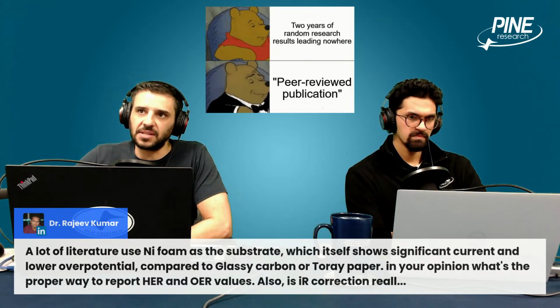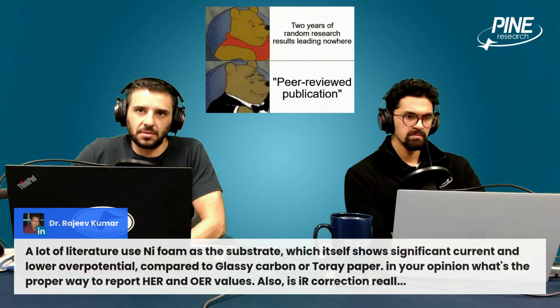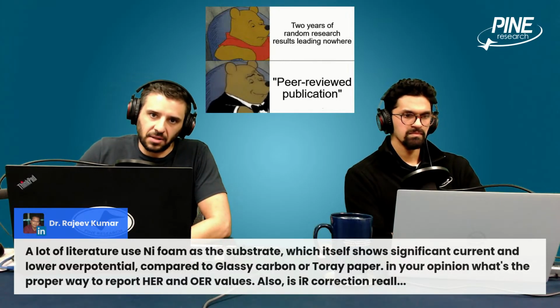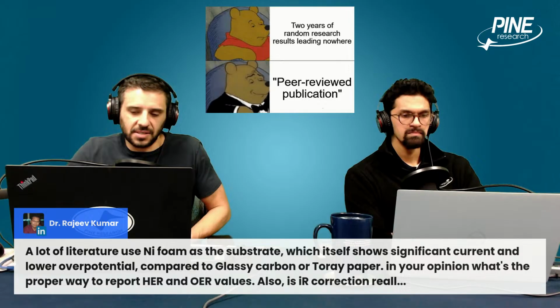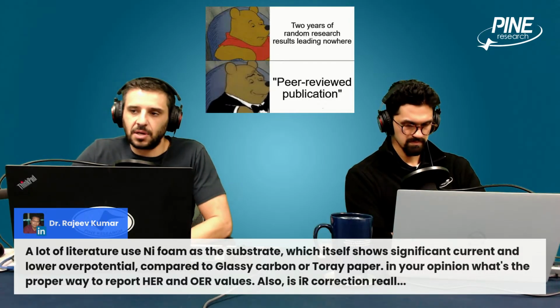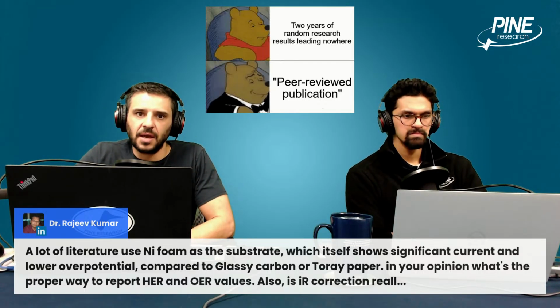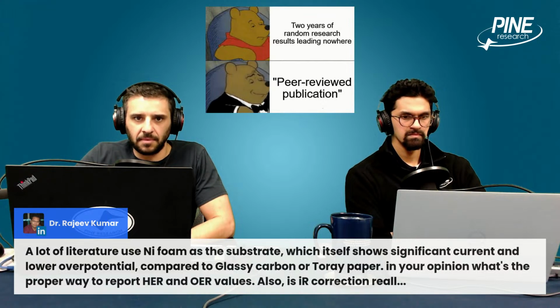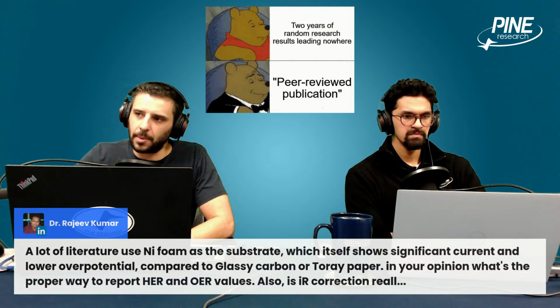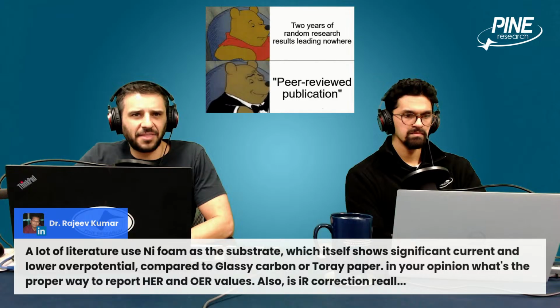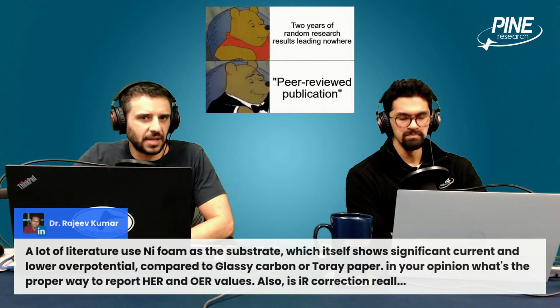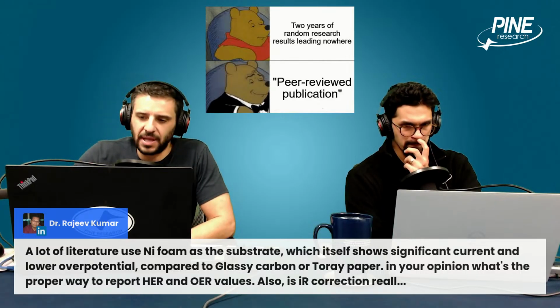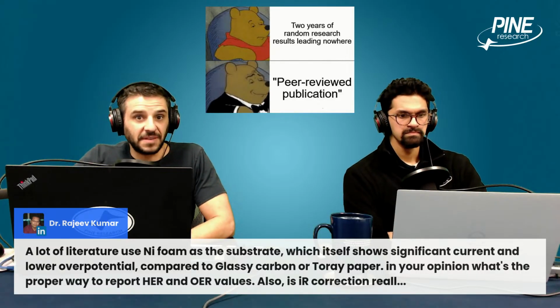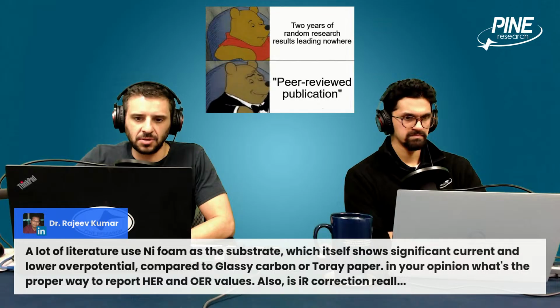I think the reason this is done is, well, there's a few of them. One of them is that nickel tends to be really good in alkaline systems, so some people prefer to use it in alkaline systems. Foam gives you higher surface area, so that helps in some ways compared to graphite, where Toray paper, carbon paper, I think carbon can be made kind of into a foam, but it's more brittle. So people like nickel foam because it's a little more stable, like physically, it's a little bit easier to use, I think.